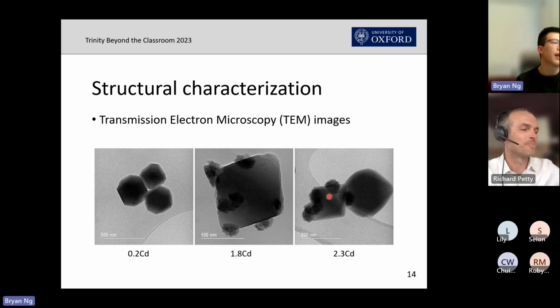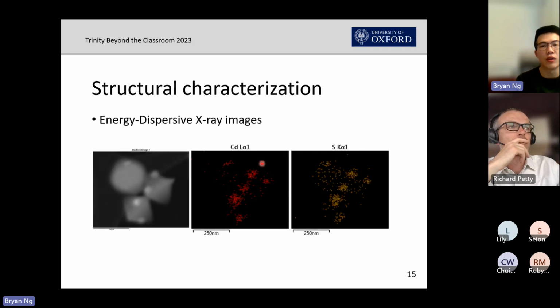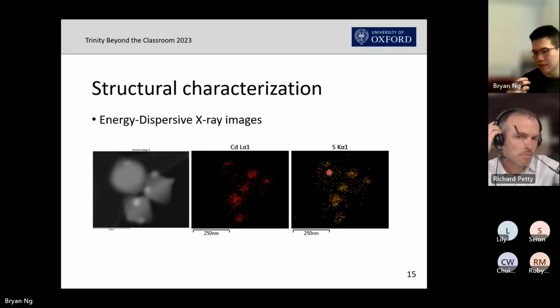Yeah, thank you. And then these darker spots, how am I able to tell what they are? There is another technique called energy dispersive X-ray imaging. This is from the 1.8 samples, I think. This is a very blurred microscopy image, maybe out of focus, but the most important thing is that we see these darker spots. This technique makes us able to see what element constitutes each pixel. For example, we see 5 darker spots on this TEM image, and then we go to the cadmium and sulfur absorption edges and see they correspond well to these darker spots geometrically. Therefore, we can draw the conclusion that cadmium and sulfur are the identity of these darker spots present on the surface of the MOFs.